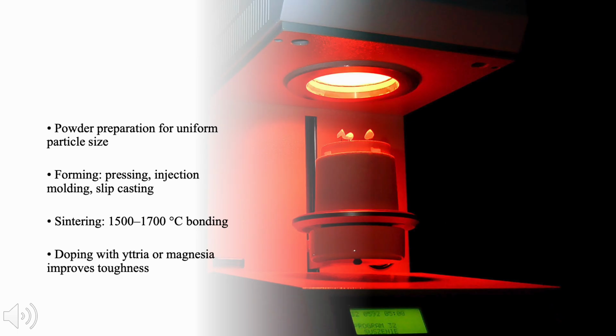Once the parts are shaped, they go through sintering. The image here shows a furnace glowing at around 1,600 to 1,700 degrees Celsius. During sintering, the individual zirconia particles fuse together, reducing porosity and forming a dense, solid structure. This step is where zirconia truly becomes ceramic. Without sintering, it's just powder. With it, we get a material that's stronger than steel at high temperatures and nearly as hard as sapphire.